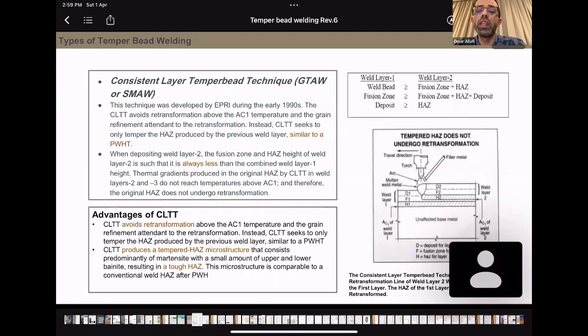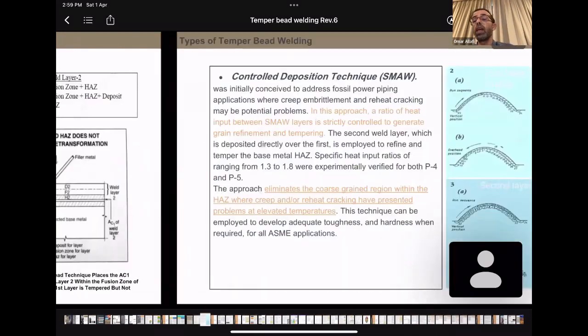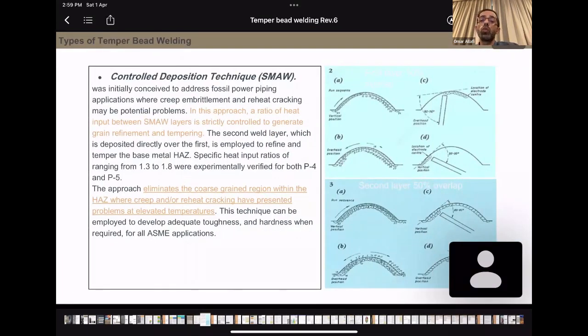So the advantages of this technique are that it avoids transformation above the AC1 temperature and produces a microstructure similar to what is achieved by PWHT. And then the controlled deposition technique. This is one of the famous techniques that is still in use to this day. This can eliminate the coarse grain region within the HAZ where creep and reheat cracking have presented problems at elevated temperatures.